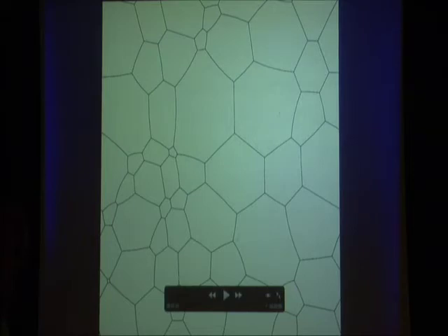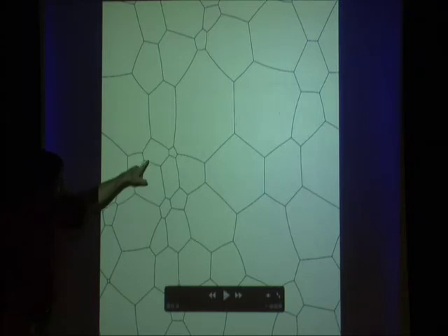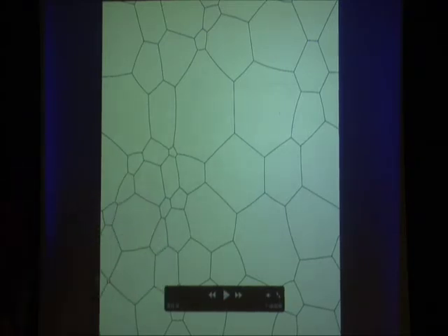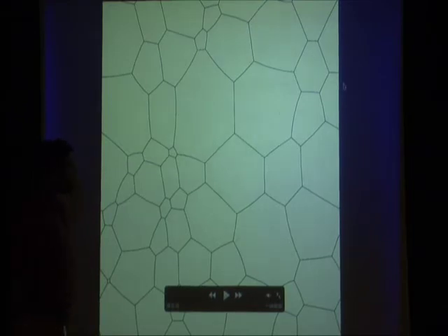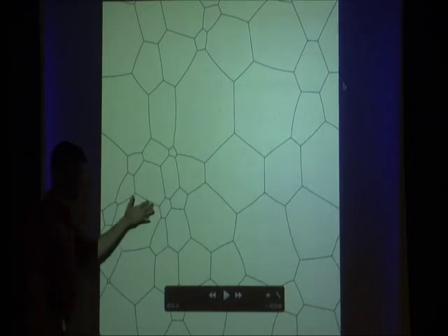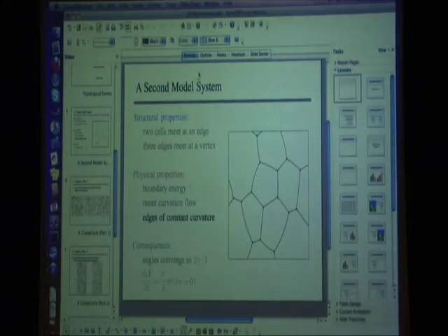Absolutely. So you can think about these as line tensions, and every one of the bubbles has a pressure. And if you do that, then I can say that in every moment the system is in mechanical equilibrium. As you look at this picture, it looks like the density is going to zero fairly quickly. Well, I'm not scaling time linearly, right? And we are working with finite systems, so what you're seeing is coarsening. That happens in physical systems. It also happens in bubbles in your beer or soap froths in your sink. Same thing. If you sit and watch them for hours, you'll see a similar kind of process.